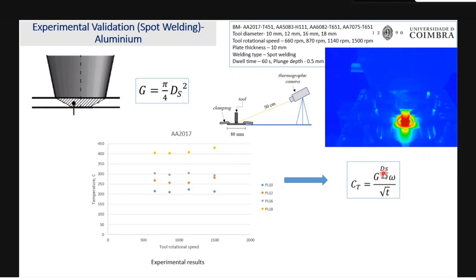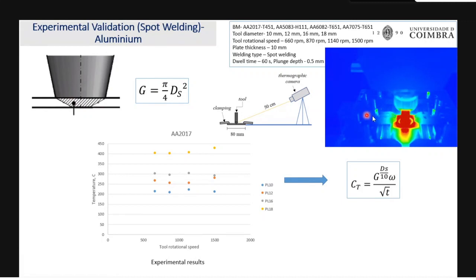And here I used ds by 10. The 10 is the thickness which I used here, and ds is the shoulder diameter. I introduce this because I need to give more weightage to the geometric parameter. So here you can see the experimental conditions and experimental results; these results were captured by using this thermographic camera, what you are seeing here.